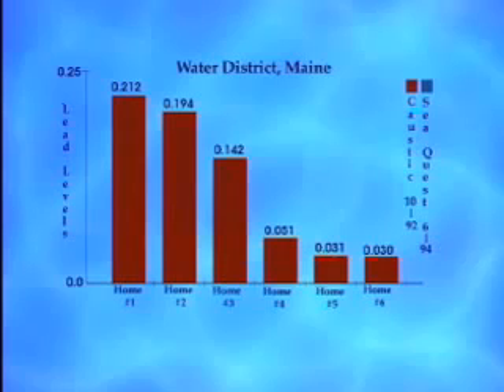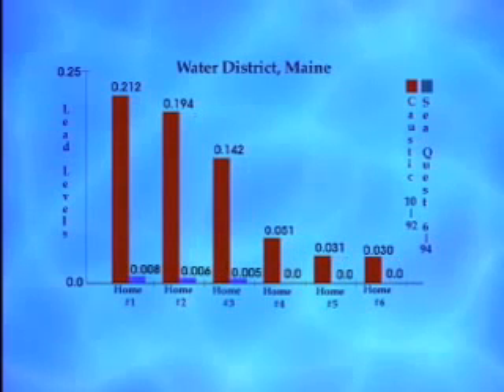Here again we see a system in Maine that was exceeding both lead and copper using caustics, raising their pH to 8.4. They then began using Seaquest and dropped their pH to 7.0. As you can see from the charts, the reduction was substantial, and where they once had 56 out of 80 draws exceeding both lead and copper, after 6 months they were down to only 2 exceeding and were now on reduced monitoring for the lead and copper regulation.